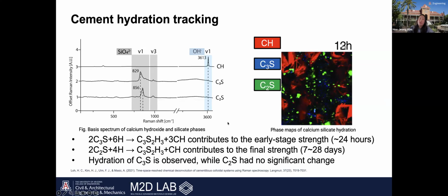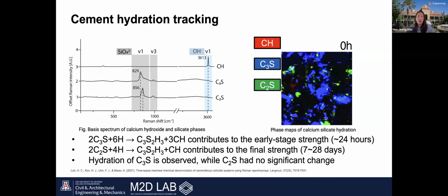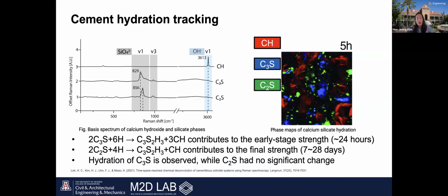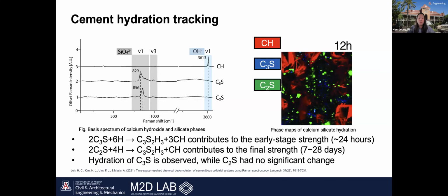So from the Raman mapping result, we can clearly see that alite, which is C3S, is gradually consumed during hydration, while calcium hydroxide continuously increases over time, confirming the progress of the hydration reaction. In contrast, belite, which is C2S, shows no significant changes during this period because it mainly contributes to the later strength development of concrete.